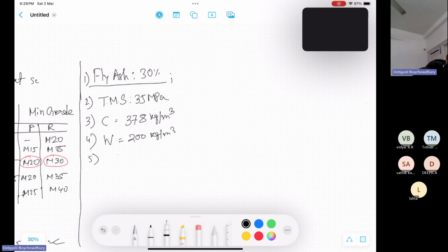Fine aggregate content is 678 kg per meter cube. And coarse aggregate content is 1155. Actually, when you use fly ash, it is a complementary material, and it will replace the cement. So after the calculation, you will see there is some reduction in cement content, and also a reduction of coarse aggregate and fine aggregate due to the fly ash content.